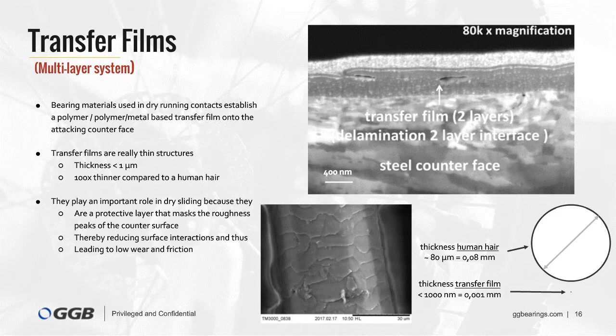When the wear debris sticks, it can form a transfer film which protects the bearing surface from further damage by the attacking counterface, reducing its wear actions. Almost all tribologically optimized bearing materials exhibit the feature of establishing a transfer film when sliding against the harder counterface. The transfer film is a very thin polymer or polymer-metal layer on the counterface.